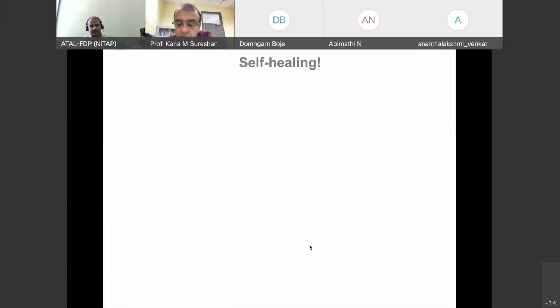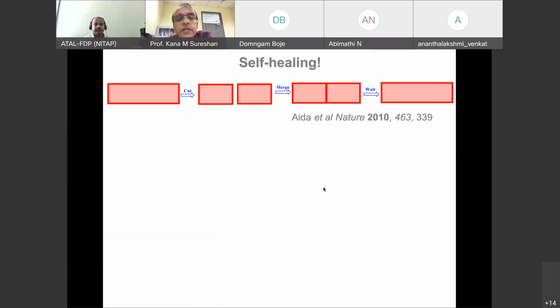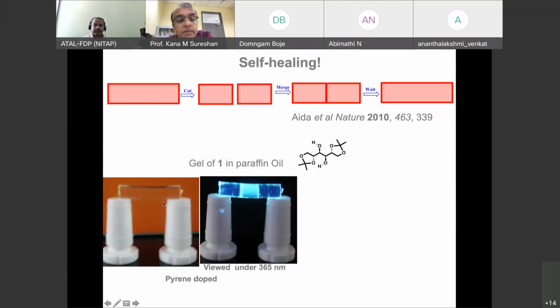Also, we found that this has a self-healing property. What I mean by that is if you cut this gel into several pieces and put them together later, it will self-heal. After some time, you can't see the boundary. This is an experiment here. The one on the left side is a gel block which we have cut into 3, and after some time it has healed. You can't see the boundary where it was cut.